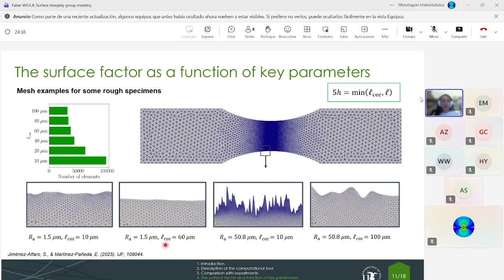Then you can see another extreme case on the other side. That is when we have a low value of the average surface roughness and a big value of the correlation length. And you can see that we may not even notice the peaks. So we need to put a rule for meshing all of these cases, especially because we have a stochastic framework. So in the end, we need to mesh several times in order to get the sample.